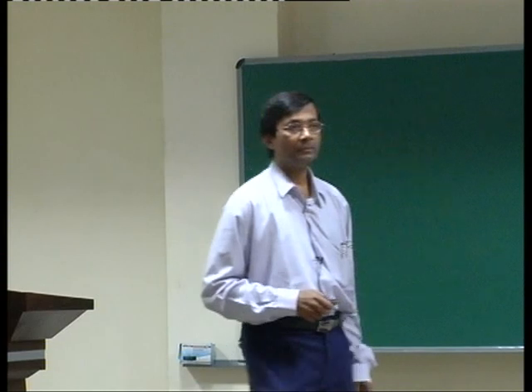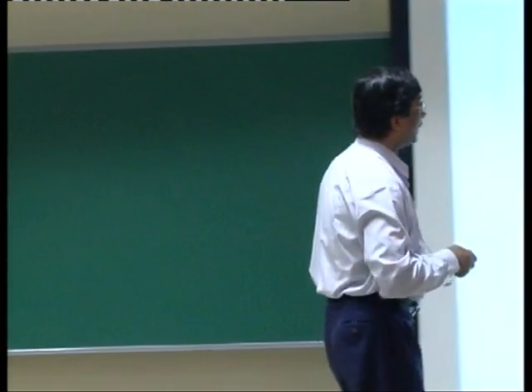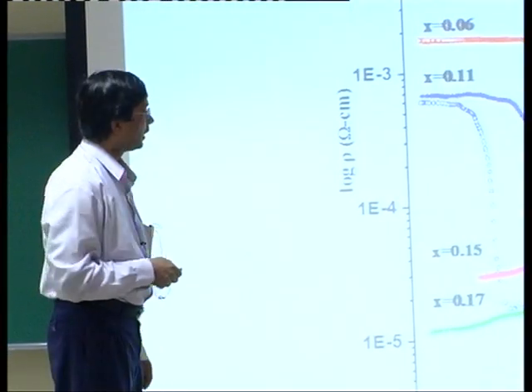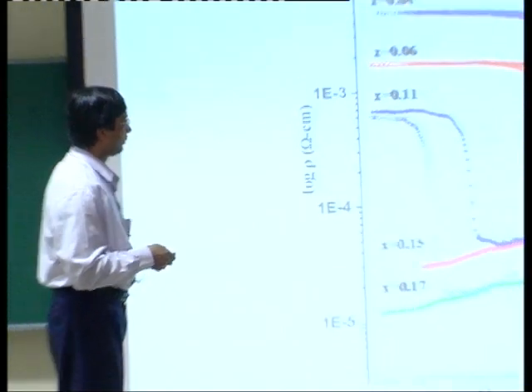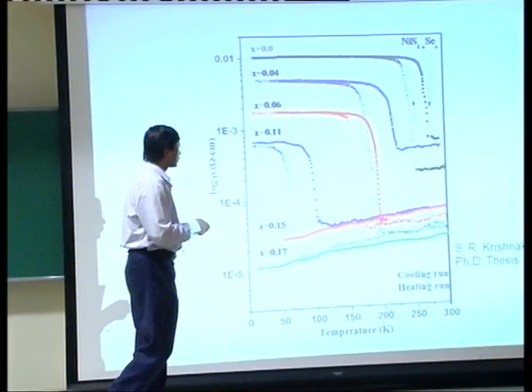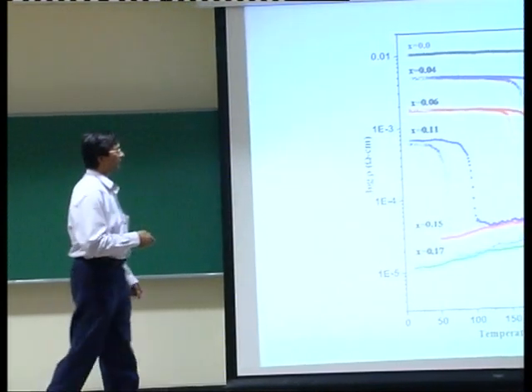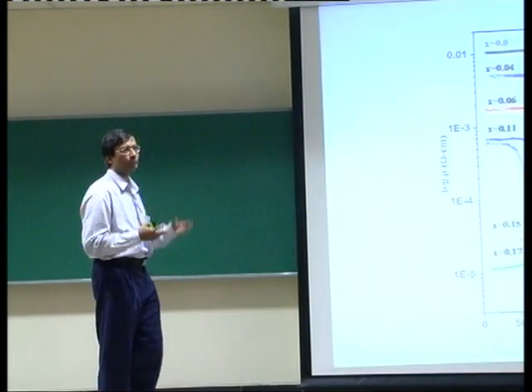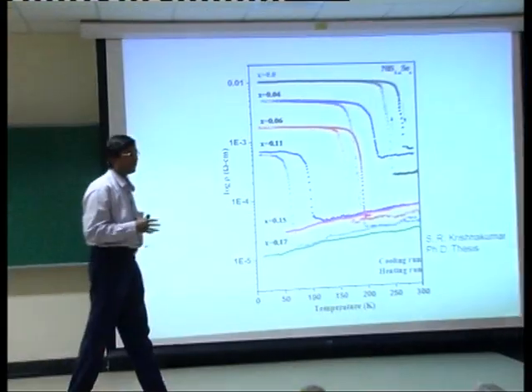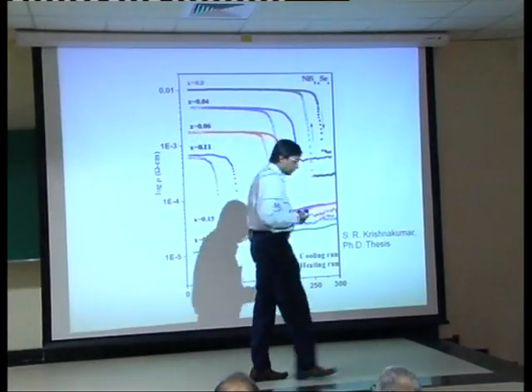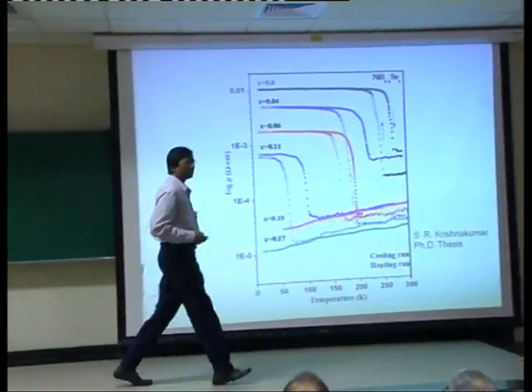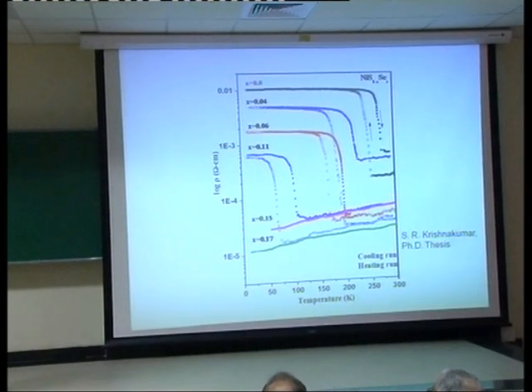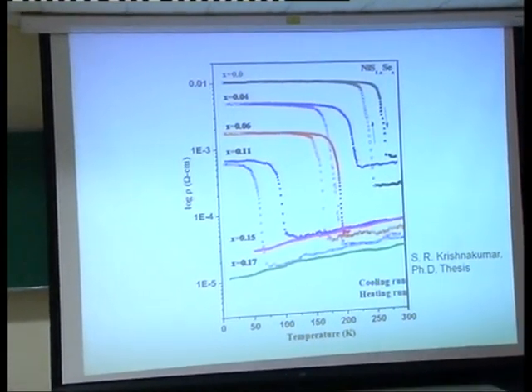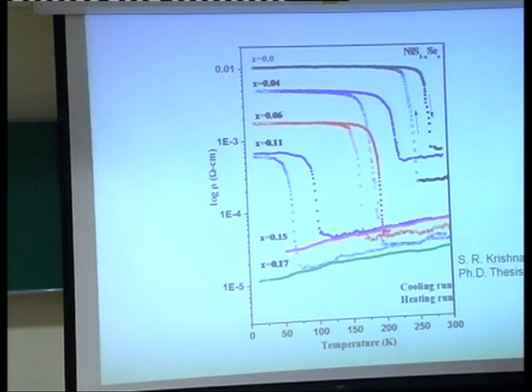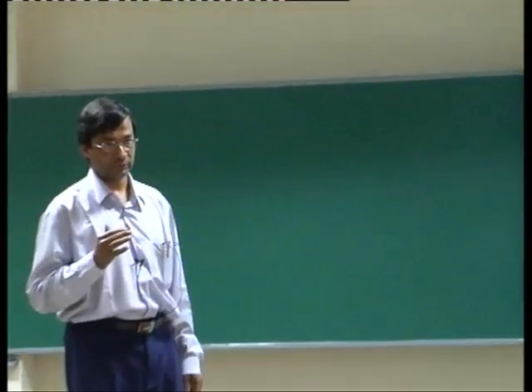So these values, this transition, it's not quite monotonic, you can see already, right? But remember, there's a larger gap. I've not plotted it and not looked at it really. So I do not know, because you have to be careful about the resistivity absolute value in a polycrystalline sample, because you have grain boundary contributions, an indeterminate amount. So that is a bit of a difficult thing.